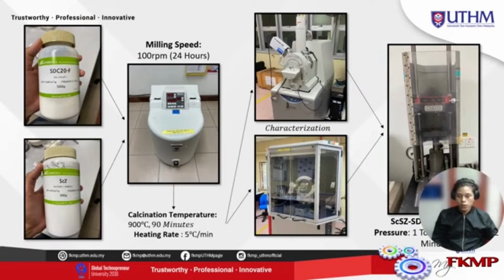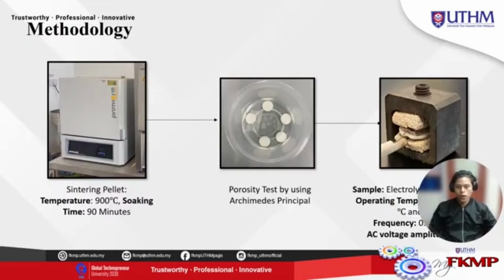Then we go to characterization. SEM checks the proper mixing of every ratio and agglomeration of the two powders. SEM can also do EDX mapping to see the separation of the elements and the distribution percentage of every element in SCSZ-SDC. Next is XRD, to identify the chemical compatibility and the elements inside, and also find the crystal size of the SCSZ-SDC. Next is pressing, 0.5 gram at 1 ton, with a holding time of 2 minutes. After pressing, we go to the sintering process, which strengthens the pellet.